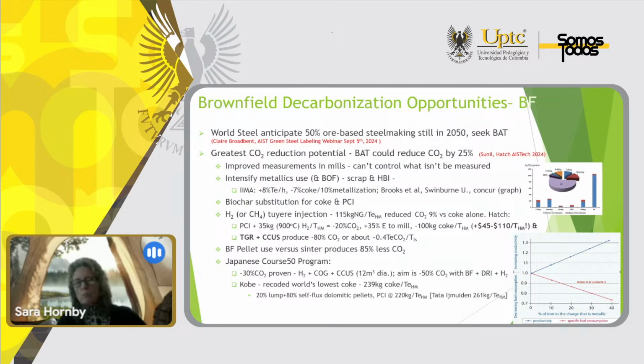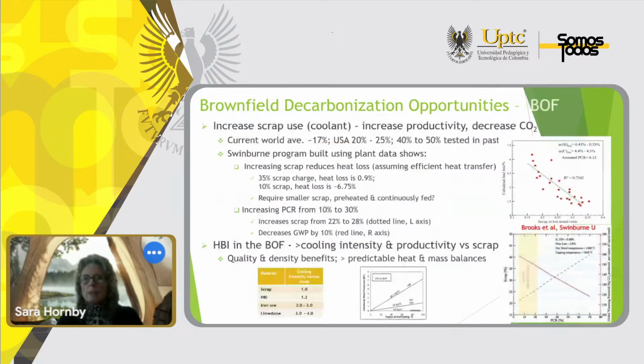Another way to save is using blast furnace pellets versus sinter, which will give you an 85% less CO2 generation. And the Japanese COURSE50 program has proven already you can get a 30% reduction in CO2 using hydrogen, coke oven gas, and CCUS on a 12 cubic meter blast furnace, which is small. Their aim is to produce a 50% reduction in CO2 with blast furnace DRI and hydrogen use. And again, Kobe Steel has the record of 239 kilograms of coke per ton of liquid steel using actually the HBI in the blast furnace.